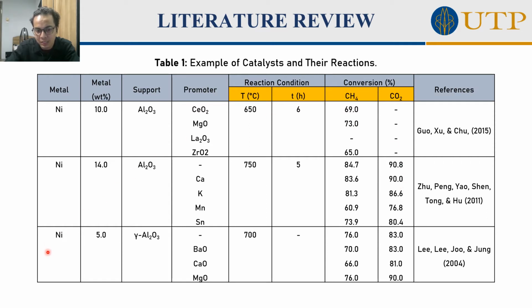The last one is nickel 5%, which is the same as ours, 5%, and it uses gamma alumina. One of the promoters is the same, which is calcium oxide. The conversion is around 66% for methane and 81% for CO2. So from here we can expect the results of the conversion for our catalyst later on.